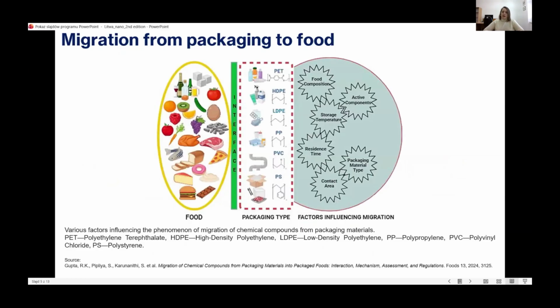Moreover, the extent of migration is influenced by the type of polymer used, the thickness and structure of the material, contact area, duration of contact, and the composition of the food itself. Different polymers show different migration profiles. The highest levels of additive migration are typically observed in polyvinyl chloride and polystyrene due to their lower chemical stability and higher affinity for plasticizers. In contrast, materials such as PET and PP are generally more stable and exhibit lower migration rates. However, they are not completely free from releasing additives.